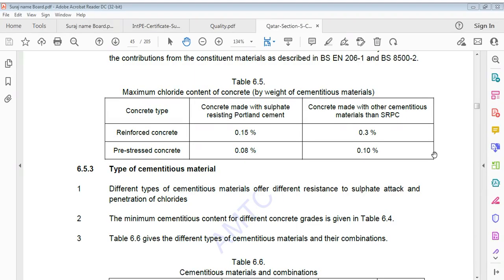it says concrete type. First, concrete made with sulfate resisting Portland cement, and then concrete made with other cementitious materials. SRPC is sulfate resisting Portland cement. For reinforced concrete made with SRPC, 0.15% is the maximum permissible chloride content. If it is other than sulfate resistant cement, I mean cementitious materials based on supplementary cementing material, it is 0.3%, which means it can take double. For prestressed concrete it is 0.08%, half of what we take in ordinary reinforced concrete, and here it can take more than that.